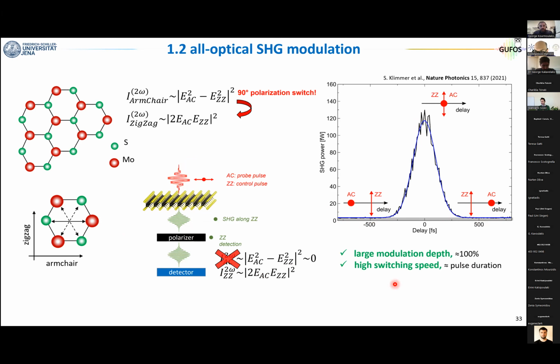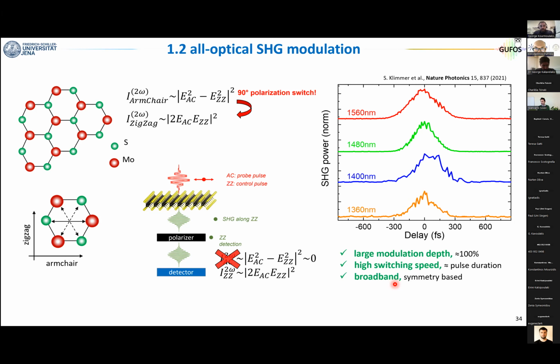So with this very simple approach, we get the largest possible modulation depth, really 100%. The highest possible switching speed, because this time we are not limited by the dynamics of the excited state, but only by the pulse duration. But we also get the largest possible bandwidth, because now you can do this for any wavelength that you want, and you don't need it to be resonant. And now if you want, this approach is somehow the equivalent of a half-wave plate. So this TMD is a very efficient nonlinear and ultra-fast half-wave plate, where you can rotate the polarization by 90 degrees on a time scale limited by the pulse duration.